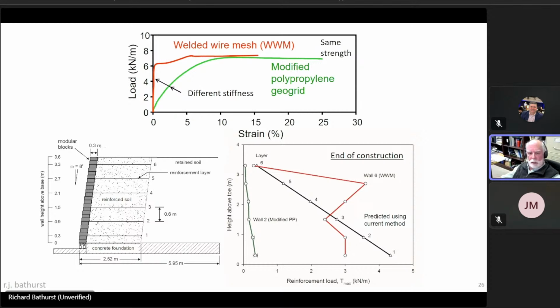And you can see clearly that the polypropylene material, the extensible geosynthetic reinforcement, generated much lower loads than the stiffer reinforcement, which is really not unexpected in hindsight, because these stiffer reinforcing elements will attract more load. But importantly, you can see that a simplified load model predicts that the loads will increase linearly with depth, which is clearly not what's happening for the polypropylene wall. Maybe it's not a bad prediction in practical expectations for the steel. But this model cannot predict both cases, extensible and non-extensible, to similar levels of accuracy.